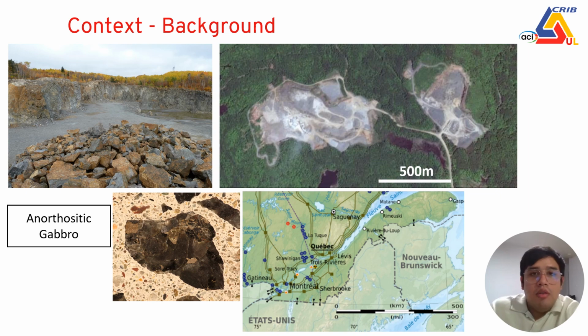This project emerged because there was a big issue in the city of Trois-Rivières. It's a small city between Quebec City and Montreal, Canada, where two quarries were supplying concrete aggregates with a high quantity of iron sulfide minerals. These iron sulfide minerals you can see here in the picture are in a brownish or yellowish color, and they are composed of iron and sulfur, so they can be really attacked by environmental conditions. As you can see in the picture above, there is a lot of erosion already done on the rock material.